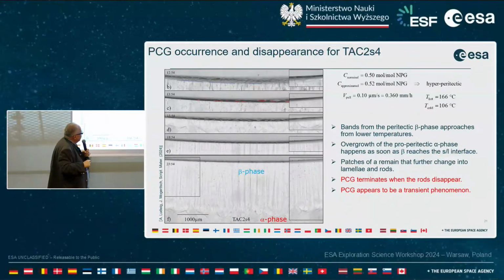But then there's one question that we have between hypo- and hyperperitectic. It seems that for the hypoperitectic phase, they grow more or less constant, whereas for the hyperperitectic phase, they form triangles like here that get smaller and smaller and disappear. But we still have open questions about this transient phenomenon.